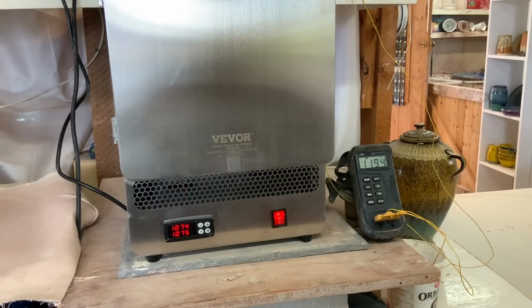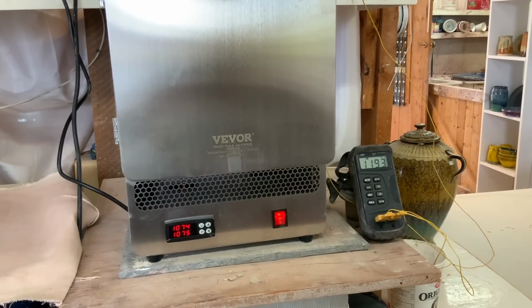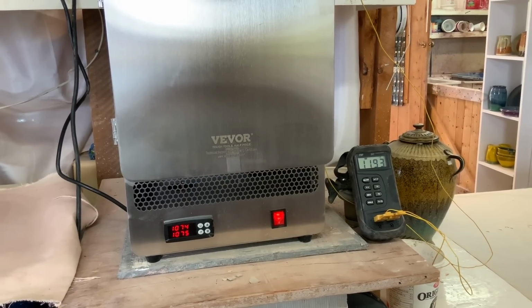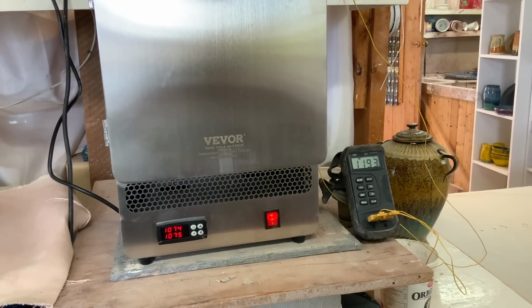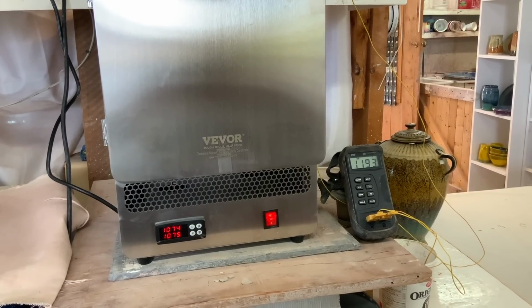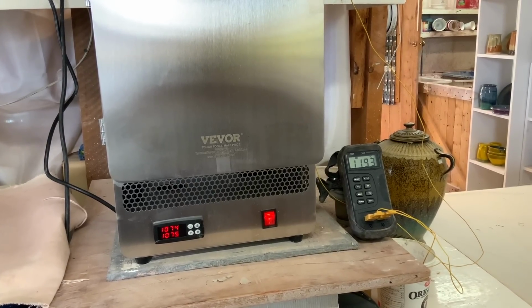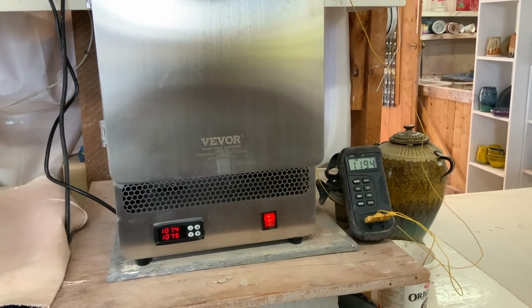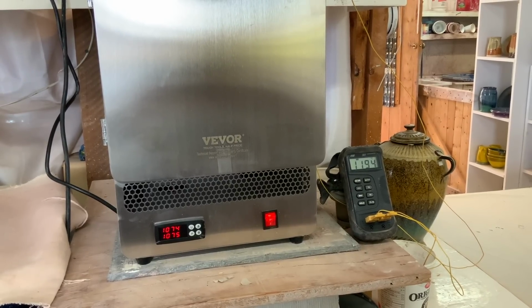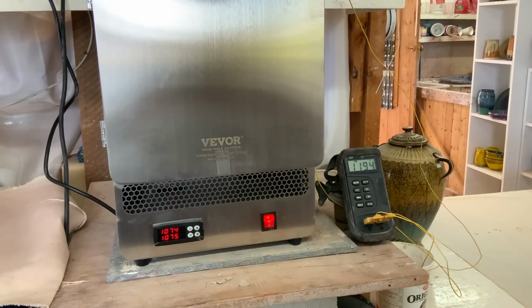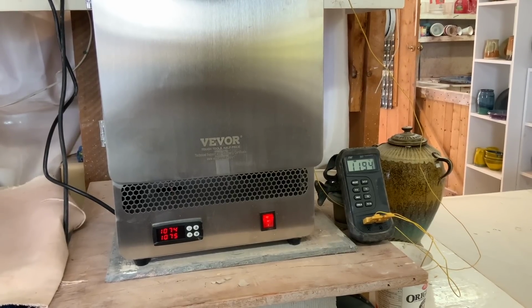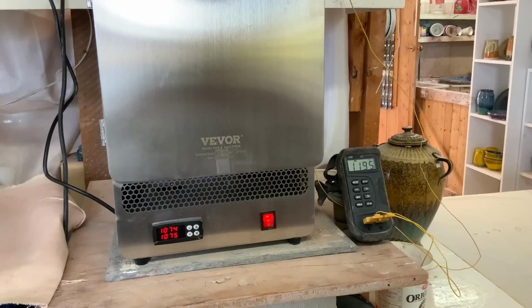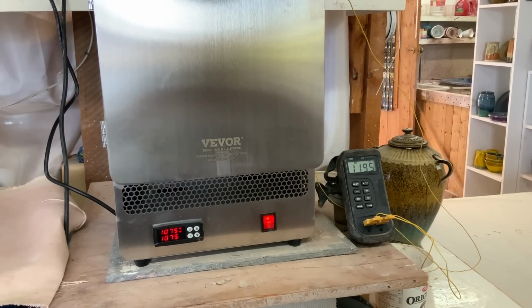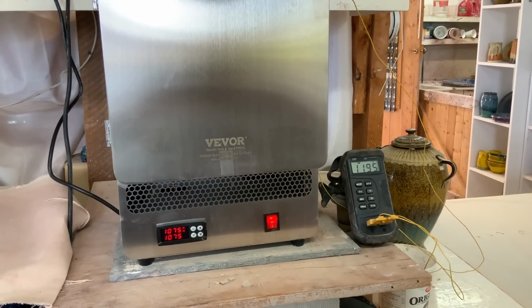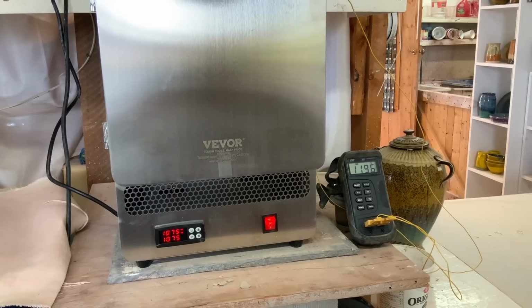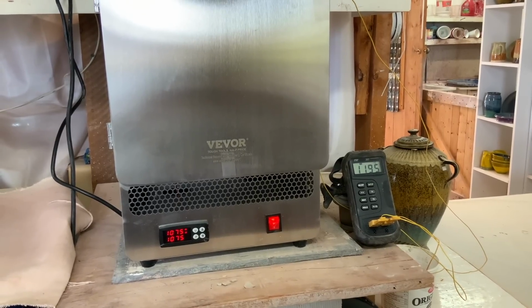So I think we have to assume that you're going to have to set this kiln between 1075 and 1100 to actually get a cone 6 accurately, which shouldn't be, but that's the way it is. And so you can use this kiln. It's actually perfectly functional. It does a great temperature rise, but you've got to do some tweaking, and that is the difference between spending $1,800 on a test kiln or $400 on this kiln.